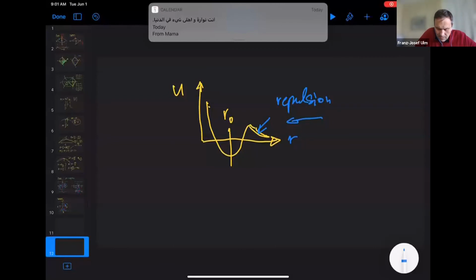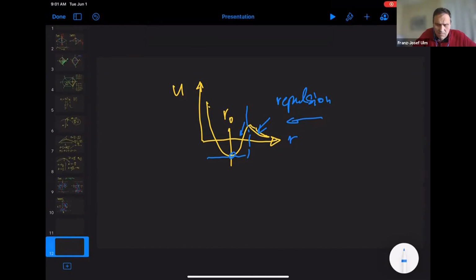And I think that is correct. But at some stage here, our material will gel actually, and it will bypass a percolation threshold, beyond which the distance between particles is such that they are attracted. And ultimately, they want to come here to this equilibrium stage. So this is the way people have started looking at this problem from a completely other perspective, from particle mechanics, backed up by results from Nonat, who has made measurements by AFM with a functionalized tip, where he measured, depending on the concentration of portlandite in the solution, attraction or repulsion.